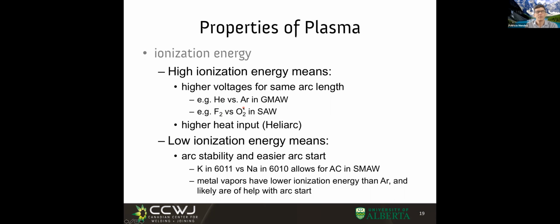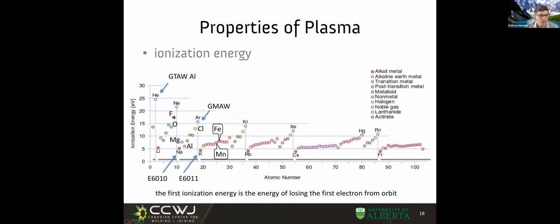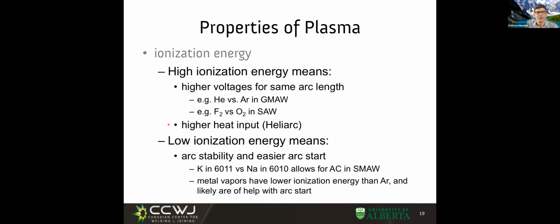It's also going to give, and we have done these experiments in submerged arc welding, if we use calcium fluoride fluxes compared with oxide fluxes, the calcium fluoride fluxes have higher voltages for the same arc length, and we could measure the arc length. And of course, this makes sense. Here's fluorine, and here's oxygen. So it makes sense. Higher ionization potential gives us higher voltage. And in this case, just by looking at the composition of the flux, I would be able to start inferring that for that weld, I need to have a higher voltage. Otherwise, I might have some episodes of short circuit.